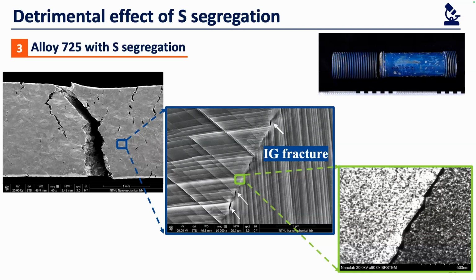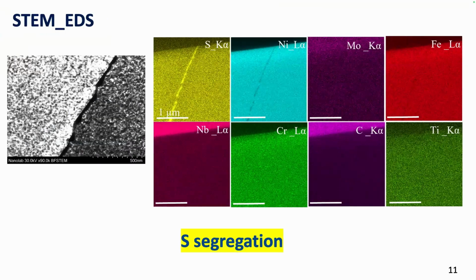And then what we see is that those interfaces have something inside. And this is not straightforward, it has a zigzag morphology. After this STEM EDS, we saw that we have a layer of sulfur at the grain boundary. And we believe it's the sulfur deposition that caused the failure of this drive screw. I still remember Professor Luo Hong also presented that sulfur deposition in high entropy alloys can be a detrimental effect.